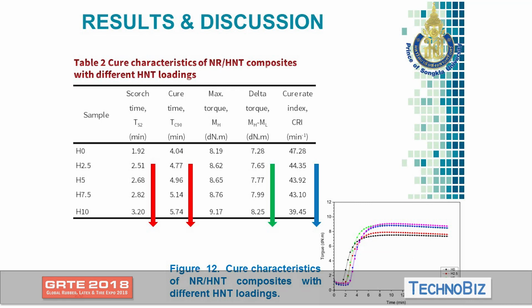Here is the result of the curing characteristics. This is very common for clay materials because they have siloxane on the surface. It will absorb the accelerators, so the vulcanizing process is delayed. The maximum torque and torque difference are also typical findings, because we include solid, rigid fillers inside the rubber matrix, so the maximum torque increases and the torque difference also increases. This is a very typical, common result.